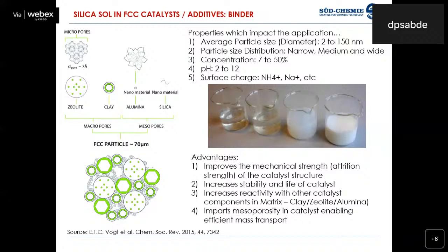There's an image included here showing the different types of silica sols available in the market. You can see there are some sols which are very clear and some which have a milky appearance. This is a visual indication: if the silica sols are colorless, we can consider the particle diameter to be less than 50 nanometers. As the size increases beyond 50 nanometers, the silica sol becomes milky.